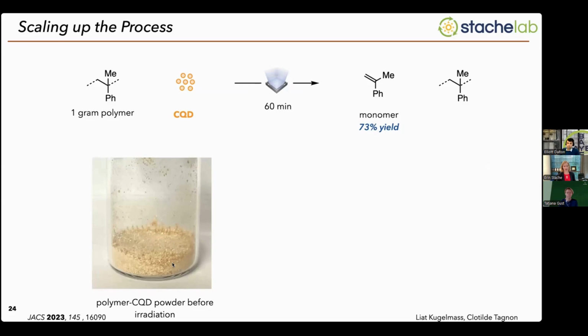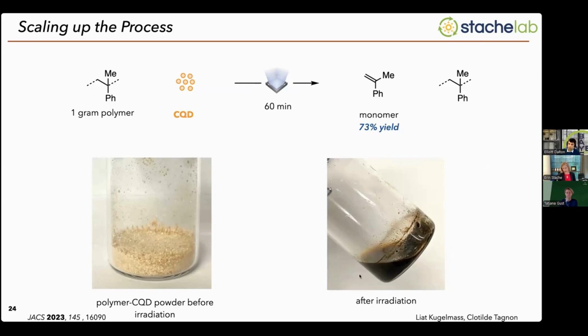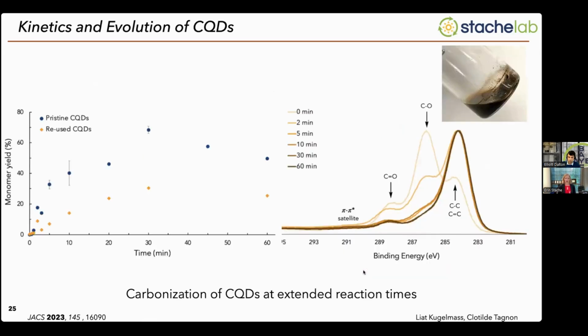We just made a powder mixture of the carbon quantum dots and poly-alpha-methylstyrene. And then you can see the solid here, and then at the end, all this liquid is the monomer that was generated. But what you'll also notice is that these beautiful orange carbon quantum dots are no longer there. Instead, we've generated this dark brown mixture. And so what we found out was happening is that the dark brown mixture was still photothermally active. What the carbon quantum dots were converted into was still photothermally active, but they were further carbonizing over time, so they weren't thermally stable. As you can see here from XPS analysis, we see that the carbon-oxygen content is decreasing, and it's basically turning into something like carbon black.